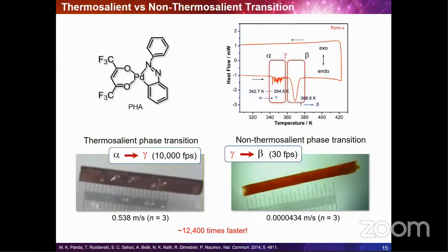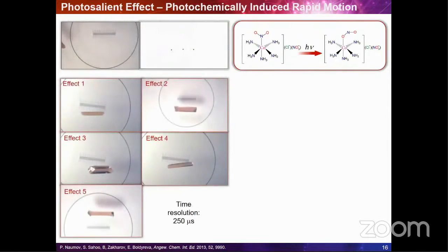Of specific interest are also transitions that can be induced by light, and we call them photosalient transitions, because in this case, you can actually control the disintegration of the crystal remotely, and you can have both time and spatial resolution. And because in most cases these salient effects are accompanied by a release of a significant amount of elastic energy within a very short period of time, they result in ballistic events and oftentimes crystal disintegration. The disintegration usually starts by generation of cracks at defect sites, which act as actuators.